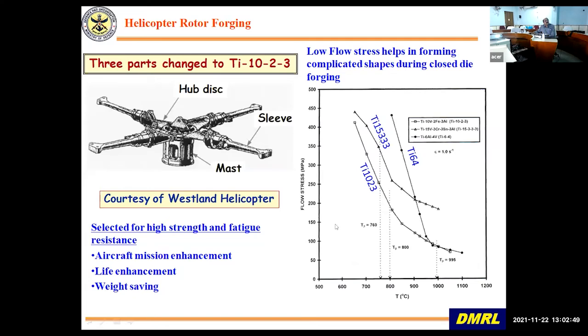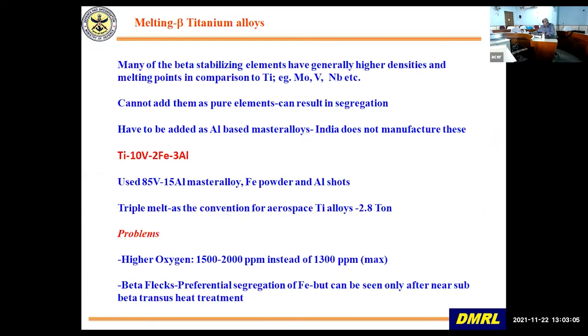You can see Ti-10-2-3 has one of the lowest flow stresses around the forging temperatures, and so it takes the shape of the die very easily. It flows very well at the forging temperatures. So that is why this beta alloy is very good for the closed die forging process.